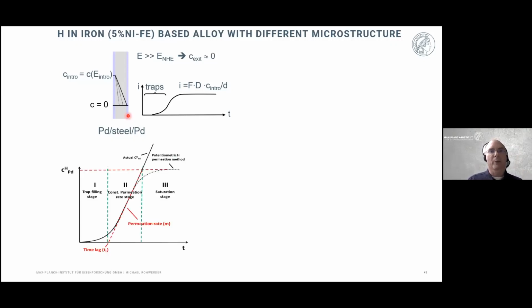On the permeation measurements, I have to say, if you use Kelvin probe, it looks a bit different. Usually, with a permeation cell, the Devanathan cell, the integrated hydrogen amount going through the sample will continue linearly, with a constant permeation current density. Here, at some point our palladium layer will reach the level where you have so much hydrogen inside the palladium layer that you get an equilibrium between hydride and hydrogen dissolved in palladium, where you get no potential response anymore, right? So you have to understand that you have only a certain time where you can measure that.